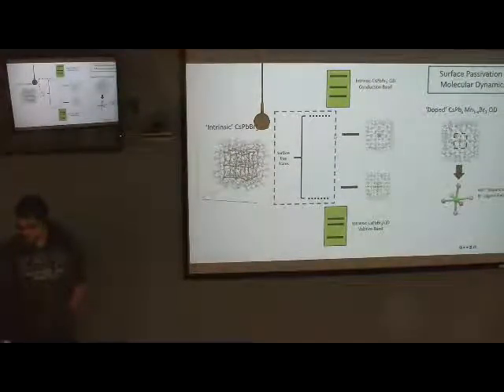So, the next thing we add to our figure: we did our electronic structure. Now we're going to look at the role that ligands can play in introducing states within the band gap, or surface trap states, which is usually reported in the literature. The expectation is that for the intrinsic dot, ligands can oscillate with the bonds, and you can see changes in oscillator strengths just due to bond vibrations, or they could even pop off during molecular dynamics. So if they pop off, or if there are any changes in oscillator strengths, you should be able to see that along your trajectory.